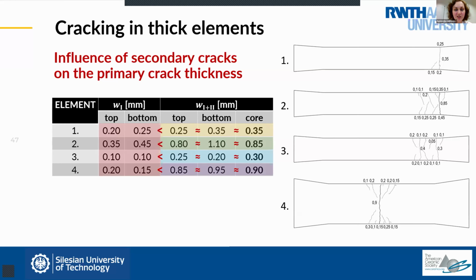And in such a situation, we would be relieved to see that the widths of the crack we see on the surface are very small. But what we are usually not aware of is that the width of the crack inside the element might be really big and reach even the magnitude of 1 millimeter, which is highly detrimental from the durability point of view.